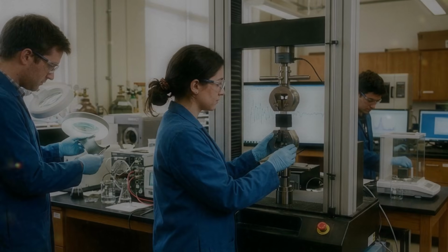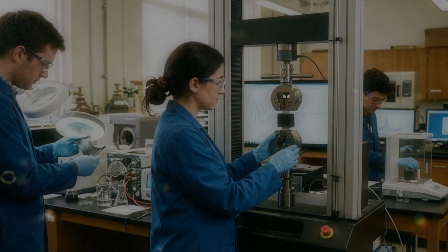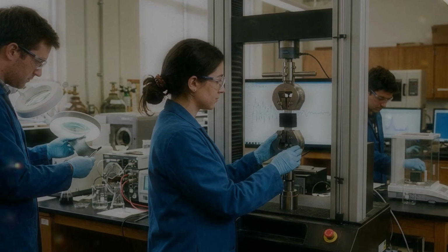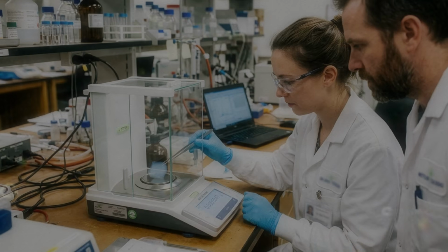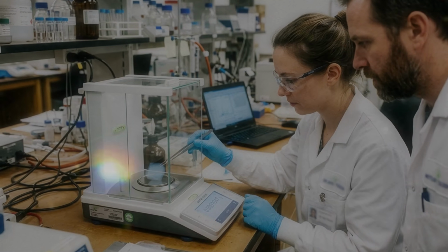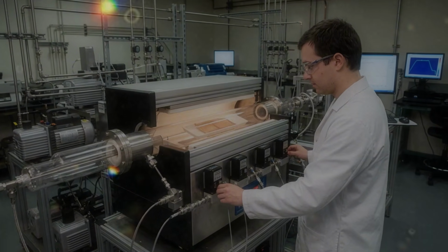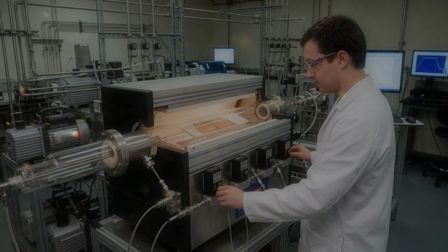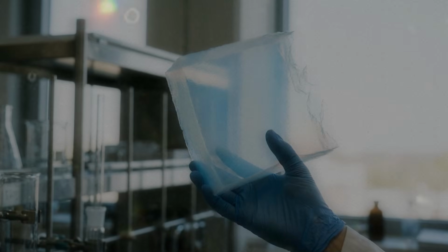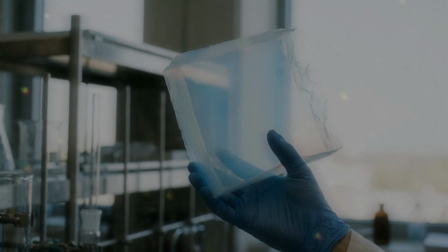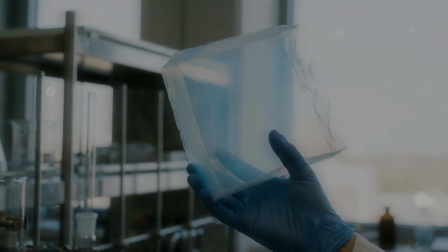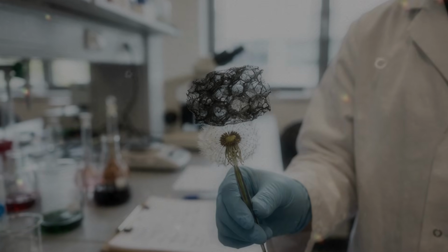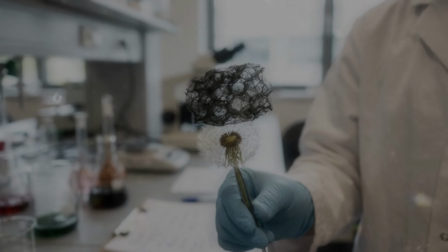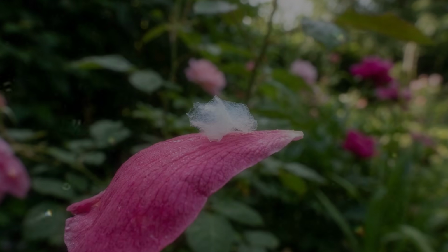Hybrid aerogels may offer the most realistic path. Graphene can provide conductivity. Metal oxides or other active substances can store charge. Polymers can improve strength. Large pores can provide transport, while small pores offer surface area. Future designs may be grown directly on a current collector, so no separate attachment is needed. Printing may place active material only where it is useful. Sensors within the porous network may detect temperature or strain before damage becomes serious. This combination of sensing and structural performance could become one of the most important directions.